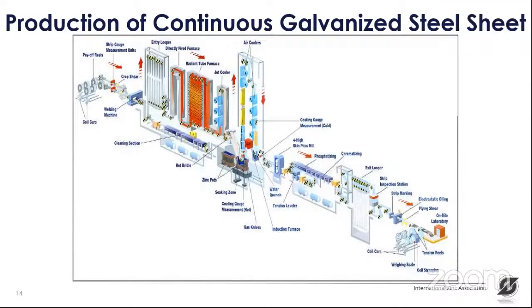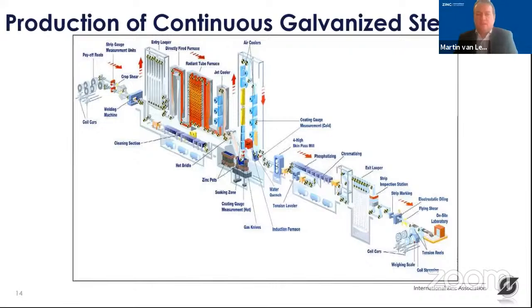No problem. So in the continuous galvanizing process, you can see that the coil starts with decoiling, and then the sheet is first cleaned again to remove all the dirt and materials on the surface that don't belong there. After that, the steel can go through a furnace process for furnace cleaning. But in these furnaces, you can also anneal the steel to change, improve or modify its mechanical properties, like elongation and tensile strength. Once the steel has passed the annealing furnaces, it is dipped into a zinc bath.